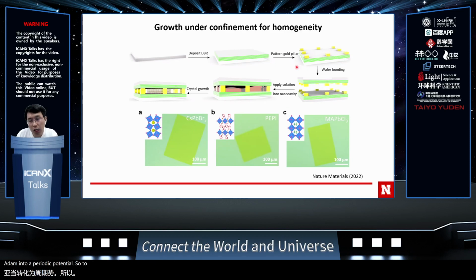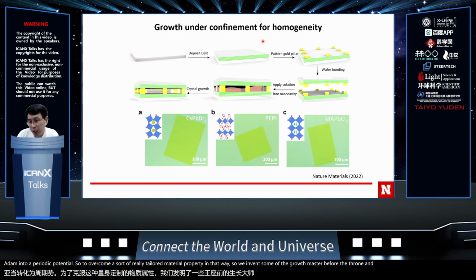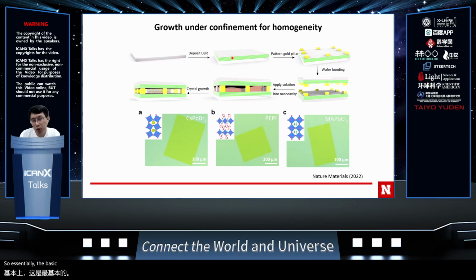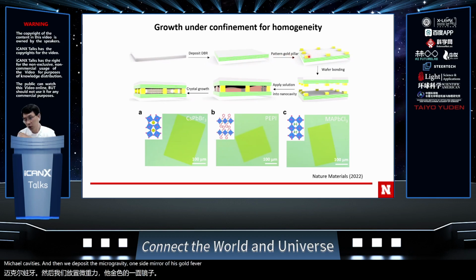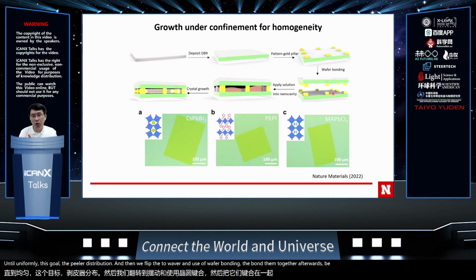So to really tailor the material property in that way, we invented a growth method. We call this growth under confinement, specially tailored for the halide perovskite material. Essentially, the basic scheme is we start with microfabrication of microcavities, and then we deposit the microcavity's one-side mirror with gold pillars, controlling the gold pillar distribution uniformly. Then we flip the two wafers and use wafer bonding to bond them together. Afterwards, we dice them into small chips.